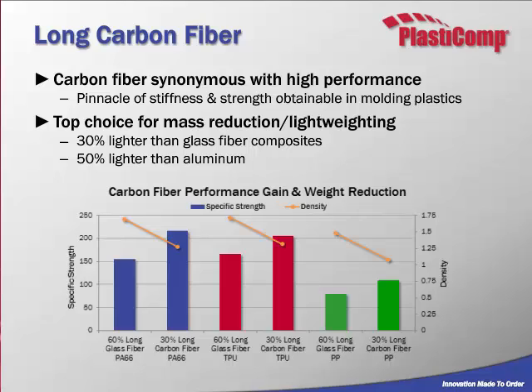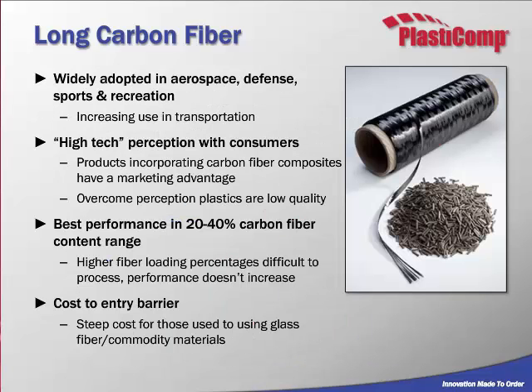Now at the bottom, you can see that we're comparing some specific strength against the density of a material. And again, you can see where carbon fiber has its value when compared against glass fiber material. Now, carbon fiber is adopted widely in performance markets such as aerospace, defense, and sports and recreation, where performance is king. That high-tech perception will only go so far. The big penalty is that the price is quite high, and that is a big entry barrier, especially in high-volume type markets. For best performance, we usually look at 20 to 40% by weight filler content. Higher loading percentages start to taper off in strength and don't give you much beyond an increase in modulus, but processing does become quite difficult.